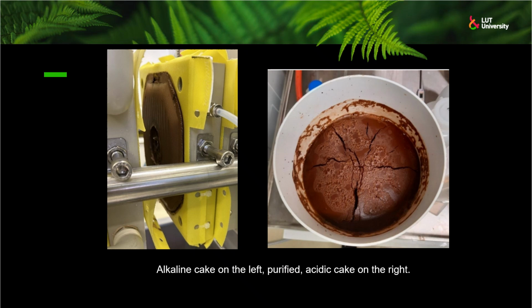Lignin cakes cracked during filtration. Due to surface cracking, some of the washing solution and neutralization water bypassed the cakes through the cracks. Using a filter press instead of a Büchner funnel in the acidic stage could have mitigated this issue.